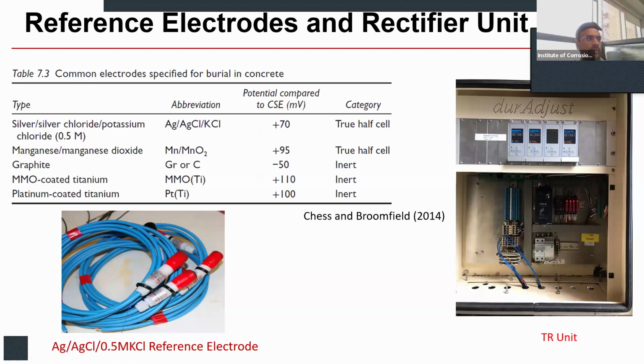These inert probes are generally used for measuring the potential difference or the decay criteria. The advantage of these probes is that they have indefinite life; however, the true half cells can sometimes get damaged. So generally it is recommended that we use a combination of both true half cell and inert probes. If the CP system is monitored using 4-hour or 24-hour decay, these inert probes can be used to monitor the decay conditions.